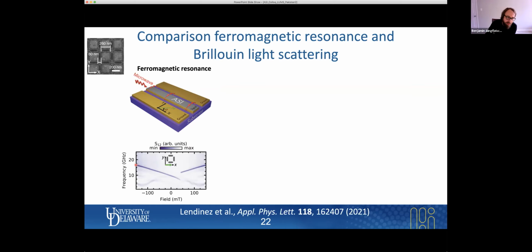And we can now see these very pronounced lines here, and this what I call W shape over here, and there are some fainter modes here and there. Now, let's think about this for a moment. In this case, I'm applying the external field, the biasing field, along the x-axis. This is illustrated by this green arrow. And I'm also showing here a schematic of the lattice. Now, these most intense lines come from elements which are patterned parallel to the external field.